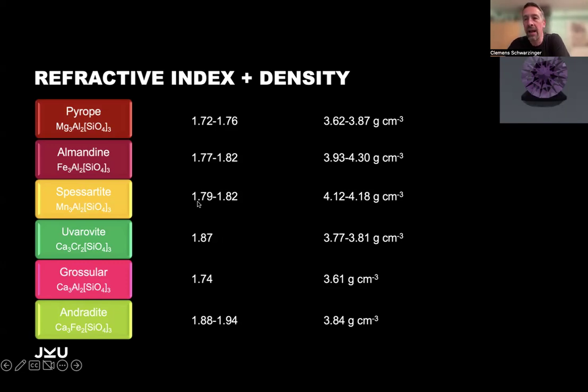So if you use LED light or if you use the classical sodium vapor lamp, or you have anything in between, the refractive index might change a little bit. And what's the reason for most of these discrepancies is that you have mixtures. There's very rarely a pure pyrope. There's always some other elements inside, and therefore you have the ranges given here. So the problem is now with 1.74, 1.75, you may fall into a couple of these categories.